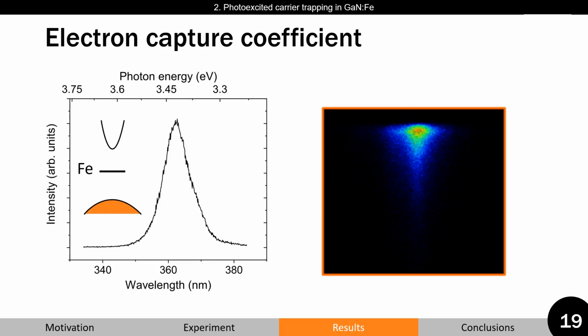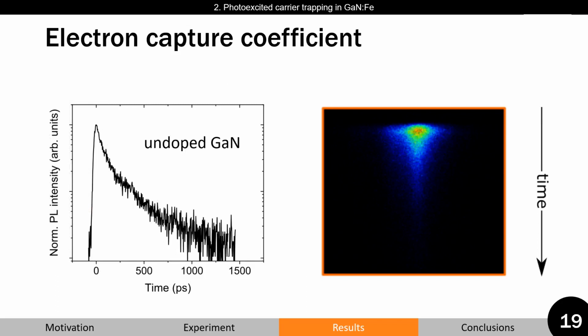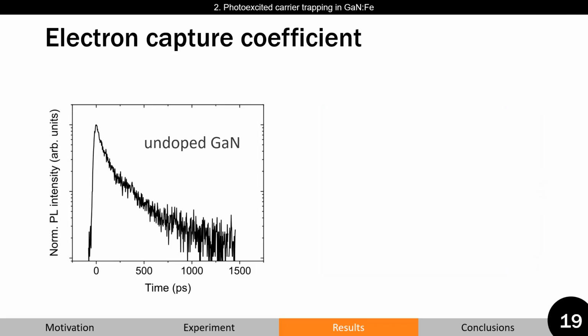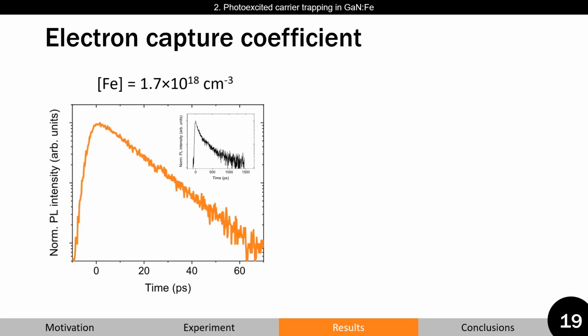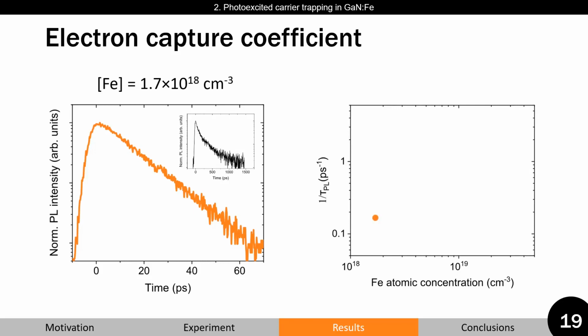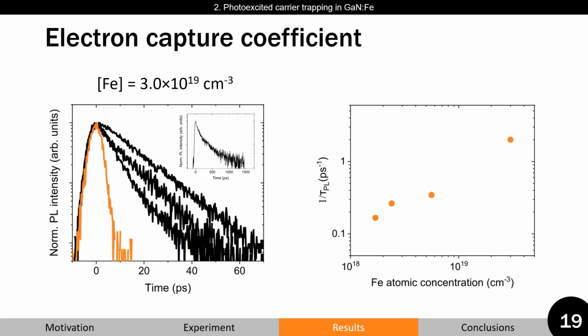First, one should check the reference sample, which wasn't intentionally doped with iron. We observed typical double exponential transients with a longer component of a few hundreds of picoseconds. Photoluminescence transients are drastically affected even with the smallest iron concentration. Samples with the lowest iron dose lead to single exponential decays with decay times of a few tens of picoseconds. By plotting decay times versus iron concentration, a linear dependence is observed.